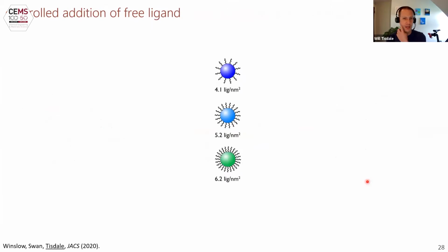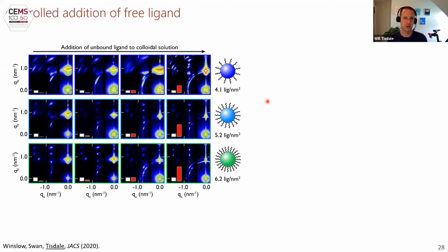So the next experiments Sam did were, rather than these random batches he had made that have very poorly controlled ligand concentration, controlled additions of ligand to very well-defined batches. So he made a single batch of nanocrystals. They're different colors, but they're all the same size nanocrystal, just with different surface-bound ligand fractions. So this is a very saturated surface with ligands. This is an undersaturated surface with ligands. And he did controlled titrations, adding free ligand to these different batches, collected a bunch of X-ray scattering data.